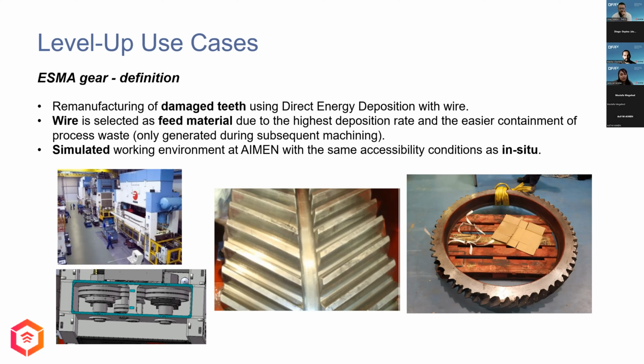And due to the different stresses generated during the stamping, some cracks and breaks appeared on the teeth. The idea is to remanufacture the lost teeth using additive manufacturing. Wire was selected as feedstock for the highest deposition rate and the easiest containment of process waste because we don't want to generate a lot of waste inside the kinematic chain of the process.